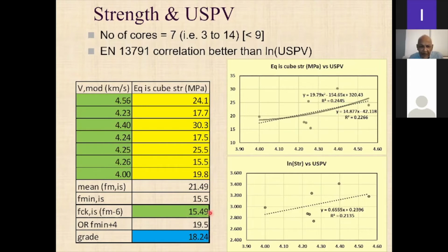And if we want to get from these cube strengths alone, this is the same one that we had earlier, and this is the grade that was estimated, right? Now, we are trying to test a much wider area using pulse velocity, and we are trying to get a correlation between these cube strengths and pulse velocity taken at the same locations, right? Now, first I want to say that I am just demonstrating a simple correlation between this and this, right? Using this polynomial recommended in the Eurocode, and using this logarithmic relationship, which I said was used earlier, right?